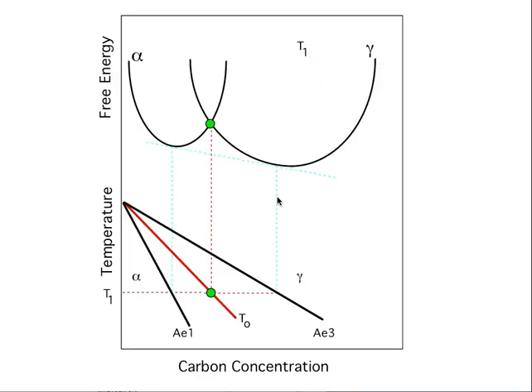Just to go through some revision: by drawing the free energy surfaces of ferrite and austenite, we can identify the locus of points where austenite and ferrite of the same chemical composition have exactly the same free energy, and that is the T0 curve, which is not normally plotted on a phase diagram because it is not an equilibrium feature.